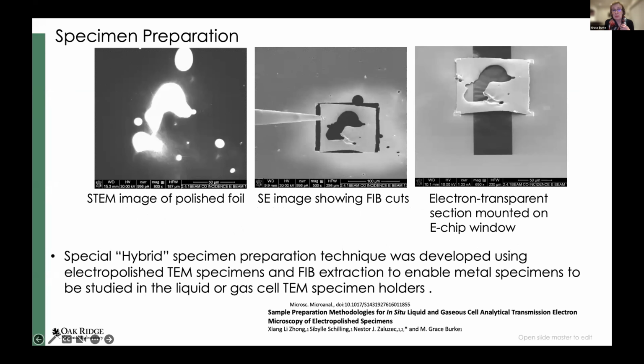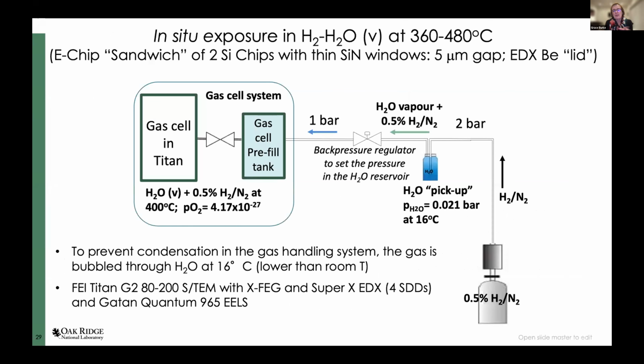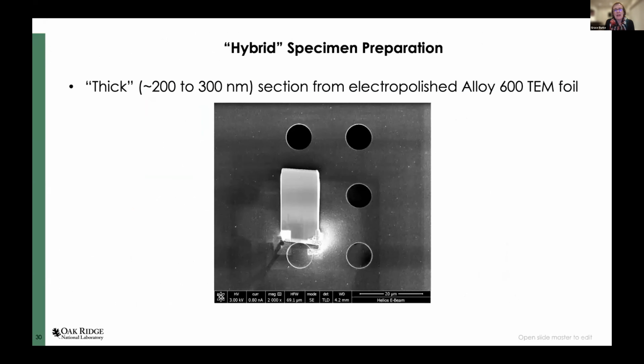This is the hybrid specimen prep technique from electropolished foils to FIB out a region of interest and then tack it down in the cell. This is not for the heating stage, but this was for a liquid cell experiment. And the schematic of what we're doing in terms of bubbling our gas through water and then into the cell. Set the pre-filled tank, and then into the gas cell. So this is what the sample looks like prior to going into the cell. And it's just tacked down with platinum on the side. So this was about 200 to 300 nanometers in thickness.